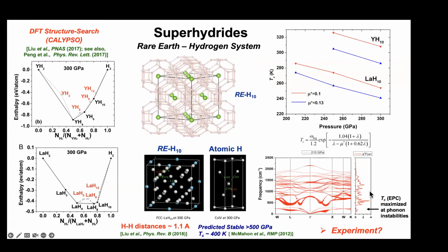And if you calculate the Tcs using standard BCS theory in various types of calculations, including Eliashberg calculations, one sees, in fact, Tcs in the neighborhood of room temperature, with this pressure dependence, with the Tc of the yttrium system being above that of lanthanum. An important point of this is that, in addition to the simple idea that you have very high Debye frequencies or average frequencies and strong electron-phonon coupling at high frequencies, at very low frequencies we also have strong electron-phonon coupling, and the highest Tcs emerge as you approach these dynamical instabilities that give the high Tc, but also limit the stability, at least in these quasi-harmonic calculations, putting a bound on the pressure dependence.